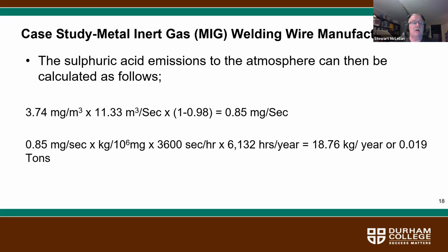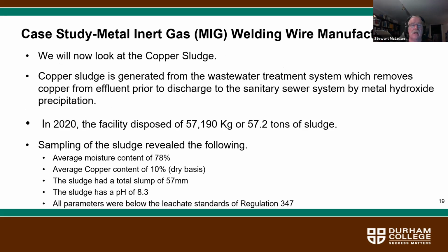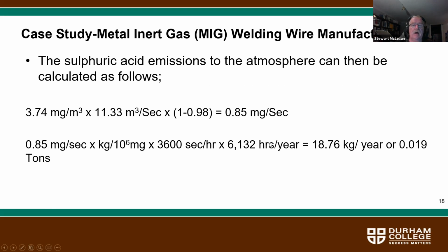0.85 milligrams per second multiplied by 1 kilogram per 1 million milligrams, multiplied by 3,600 seconds per hour, multiplied by 6,132 hours per year, gives you 18.76 kilograms per year, or essentially 0.019 tons of sulfuric acid that is discharged to the atmosphere. So you can look at that, 18.76 kilograms of sulfuric acid released to the atmosphere over a year. It's not a large amount of sulfuric acid, but it has to be quantified and it has to be reported to the NPRI.